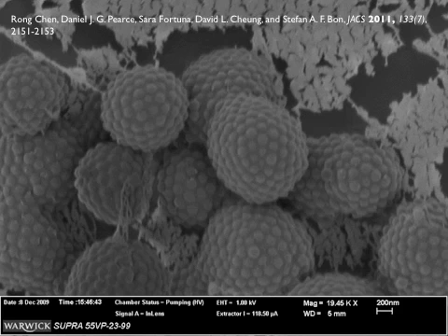So here you see the pictures that we used with these decorated vesicles. So here, these were sputtered. So what you basically see, in order to visualize these, the conducting layer, the metal layer, is these broken bits around there. So all the ice is sublimed away, and this metal blanket obviously drops over it, and you see it fractures around these vesicles, and these vesicles are beautifully decorated with polystyrene particles. So without cryo-SEM, you cannot make pictures like this. It's impossible. So it's a very, very useful technique to have.